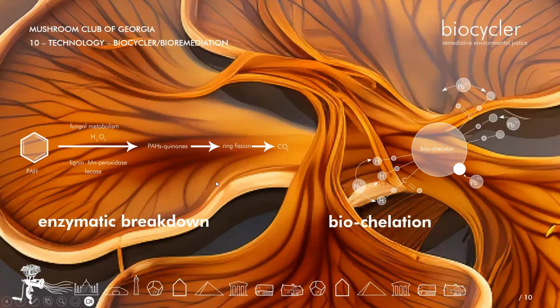Between these two mechanisms, what we're looking at doing is breaking down the long molecule chains to create safer monomers, and with the elemental toxins, things like heavy metals, attaching them to larger molecule chains that make them biologically inert. As the mycelium grows over the materials, you can also see a doubling effect, where the material that is chelated is then encapsulated by the polymeric coating of the mycelium. Mycelium is chitin rich. It has a cell wall that is very hard to digest without cooking, and that is actually beneficial in this scenario, where you can have a chelated material that is also double encapsulated with a chitinous shell.